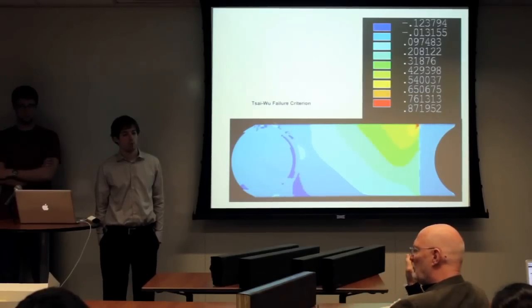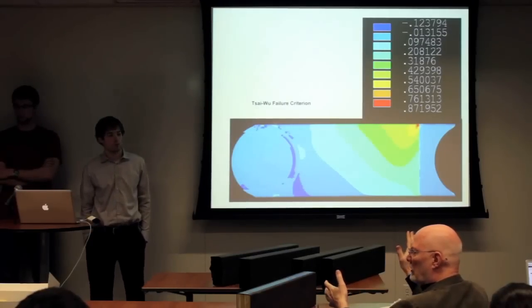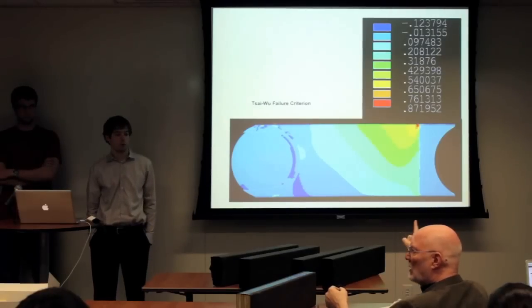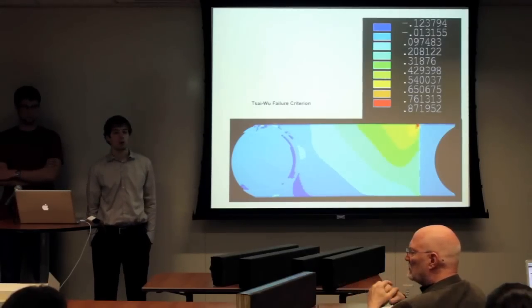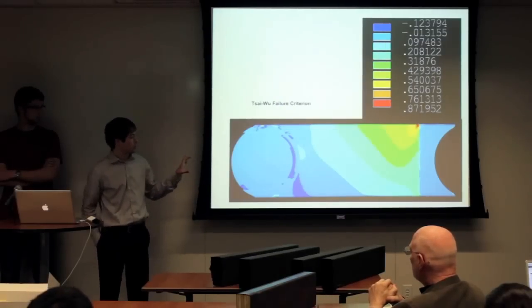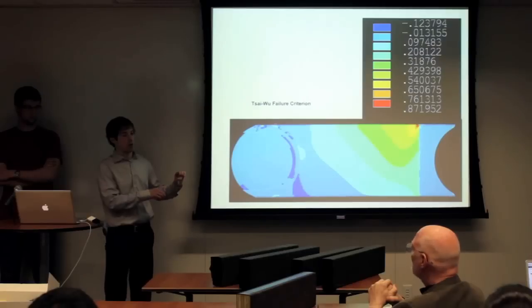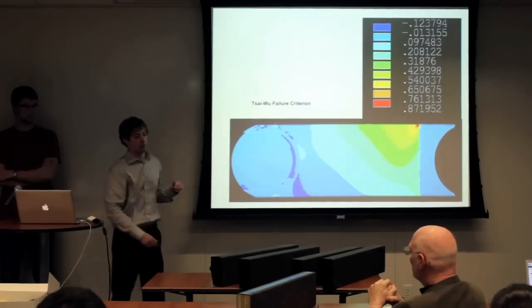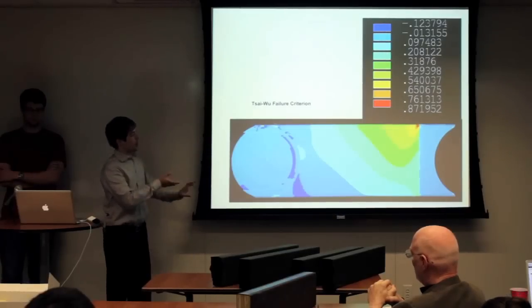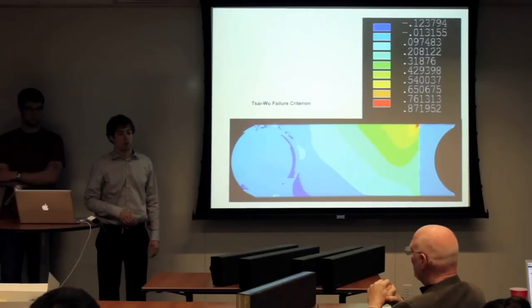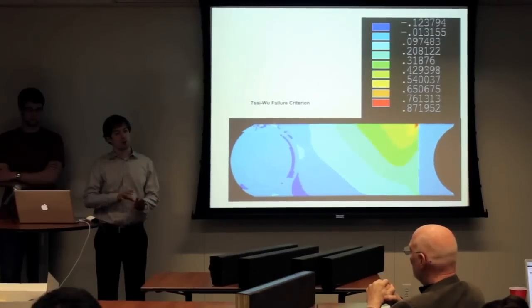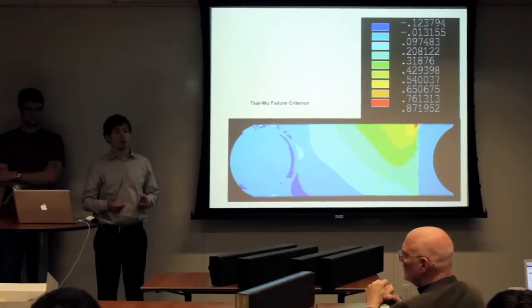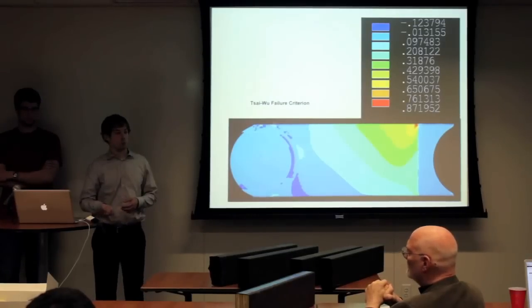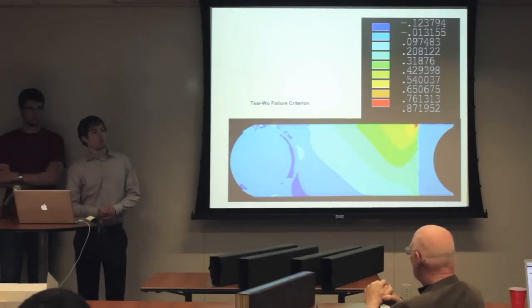So does that mean that what we're looking at is a bending, or is it bending on two axes? What is it that causes the hot spot? Okay, what causes this hot spot is actually, there are two loads. There's a torsional load and a bending load. If it was just a bending load, you would see a hot spot along the line, and that's where we expected it to break. But the hot spot is now up at the corner because it's also applying a torsional load. But when we went through the numbers, we realized that the torsional load wasn't as significant as the bending load, and the bending load would be what caused failure in the end. So that's why when we tested it, we just wanted to test the bending load. Thank you.